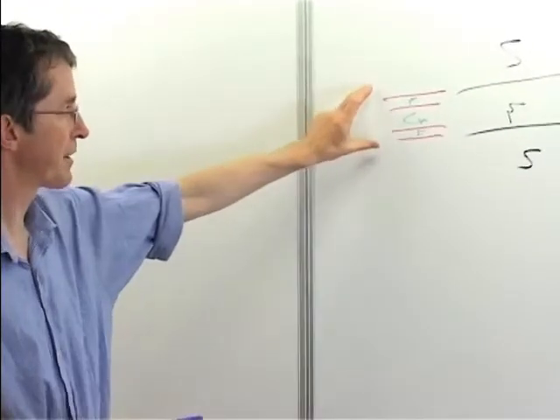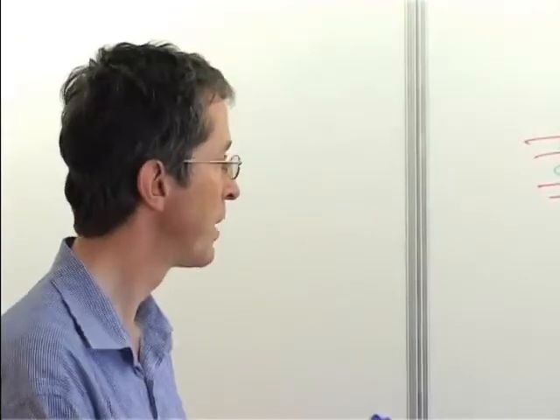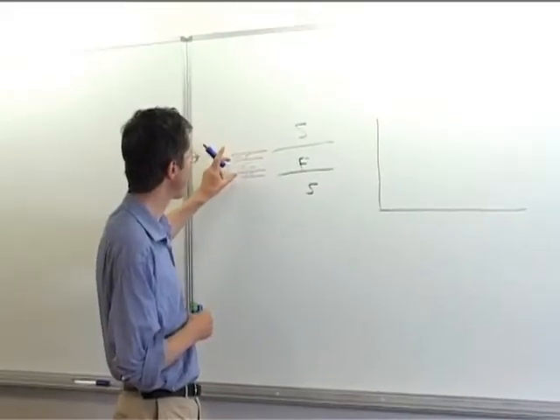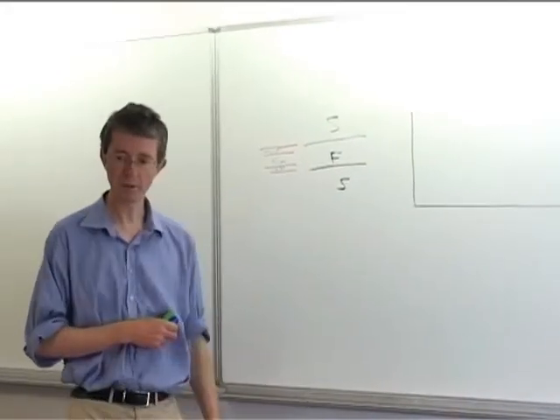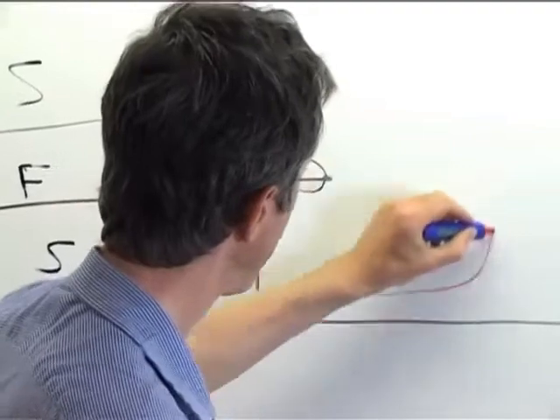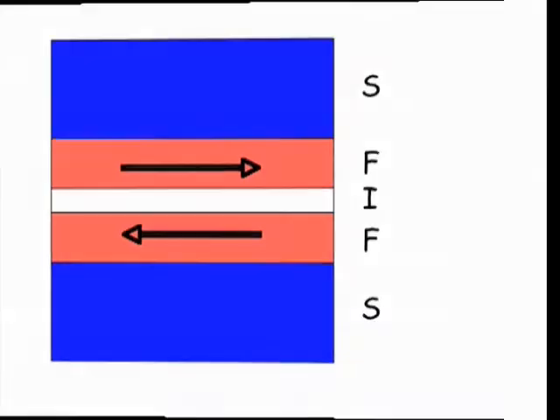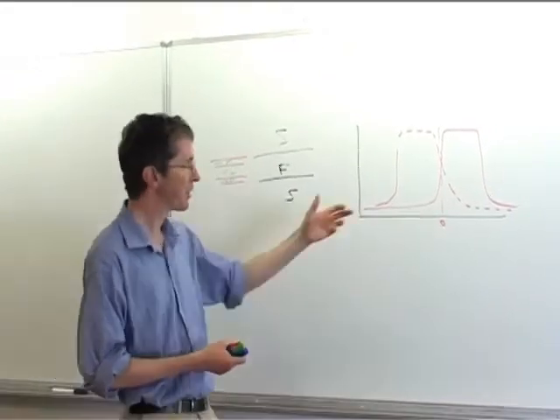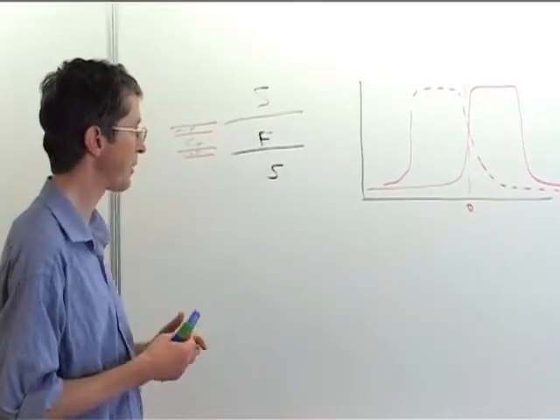This is now effectively a spin valve, so you get a change in resistance depending on whether the magnetic moments are parallel or anti-parallel. If we think just about the resistance, we have a conventional spin valve here, and the resistance rises to a high value and then drops. This is a consequence simply of the spin scattering associated with the interfaces, and we're using it here as a signature to test whether we've got the correct alignment of the ferromagnetic layers.